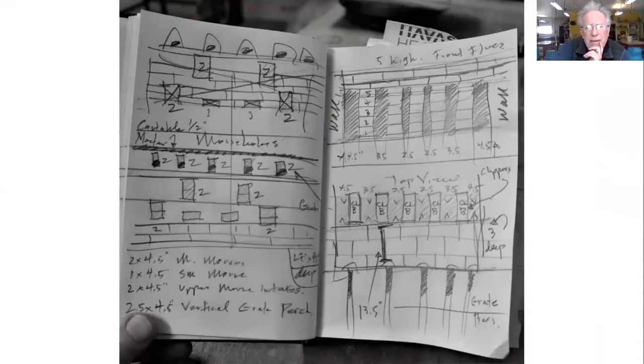Also, as we built the kiln, we kept a pretty detailed sketchbook of different measurements for primarily the flues, but also the widths of things, the width of the chimney, the height of the chimney, where did the damper end up, and so forth. Because that kiln, if you remember, was covered with a castable. So you couldn't really see a lot of these things until you got into the kiln and started to dismantle it. And I have a little bit of a funny story about that.